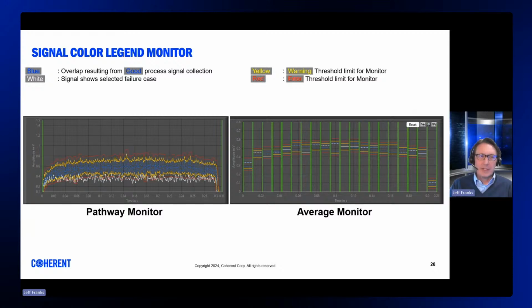The colors for the pathway are categorized as follows. Blue represents, in this case, an overlap of accumulated good signal data. Reaching either of the yellow bands would trigger a warning condition for the monitoring, the sensitivity of which can be adjusted, whilst going beyond the red would initiate an error signal from the software. The white signal on the pathway monitor is an example set of data, in this case for a bad weld or failure condition. When the pathway becomes very broad, as for example with wobble welding, then the average monitor can be utilized to enable a more stable monitoring of the process.